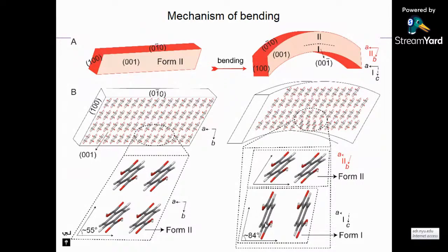This is single crystal diffraction data where you can see in form 1, the molecules are oriented at some kind of tilt angle. When it comes to the bent shape of these form 2 crystals, we have actually seen bimorphism. That means we have seen both polymorphs existing in a bent shape. As you can see, the upper layer is form 2, and the inner layer is form 1.